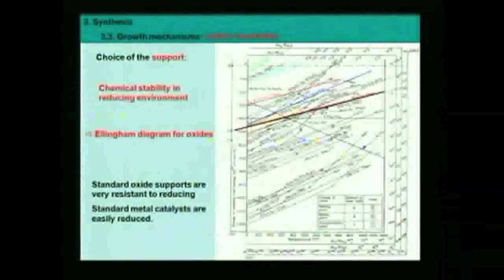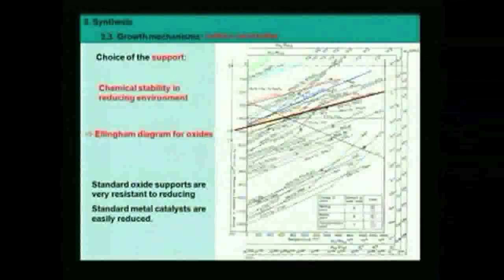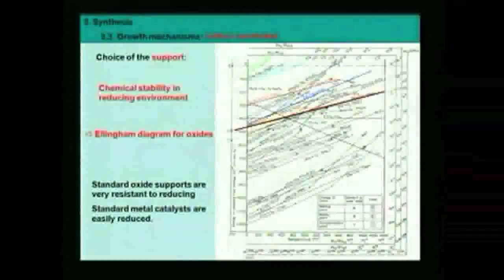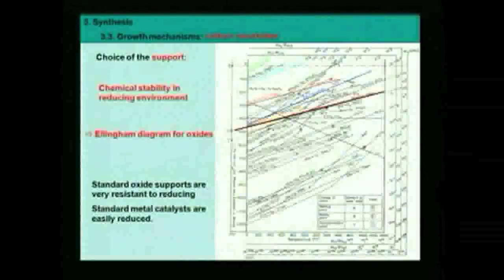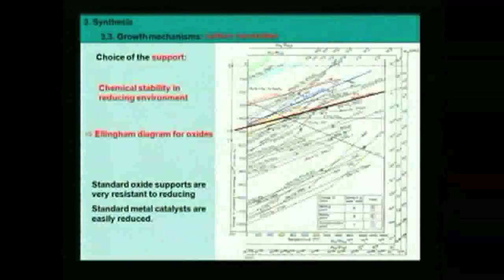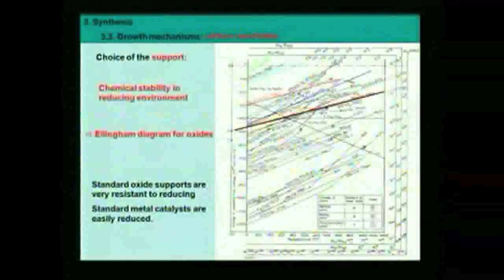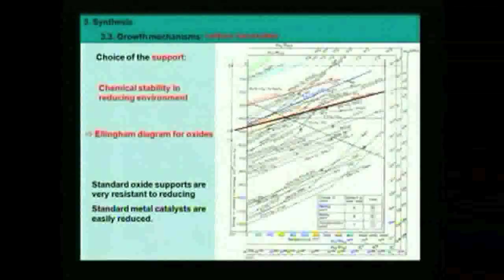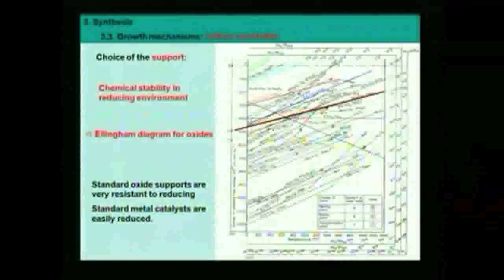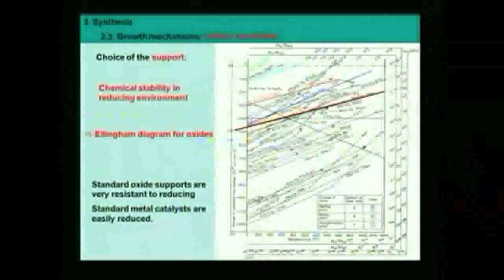We observe that silicon oxide is here. It has a very negative free energy of formation. It means it's a very stable oxide. Aluminum oxide is somewhere here. Also, it has a very negative free energy of formation. It's a very stable oxide. It will be very difficult to reduce this oxide. On the contrary, if we look at silver, silver makes a very unstable oxide. This is good for jewels, of course. It's very easy to reduce.